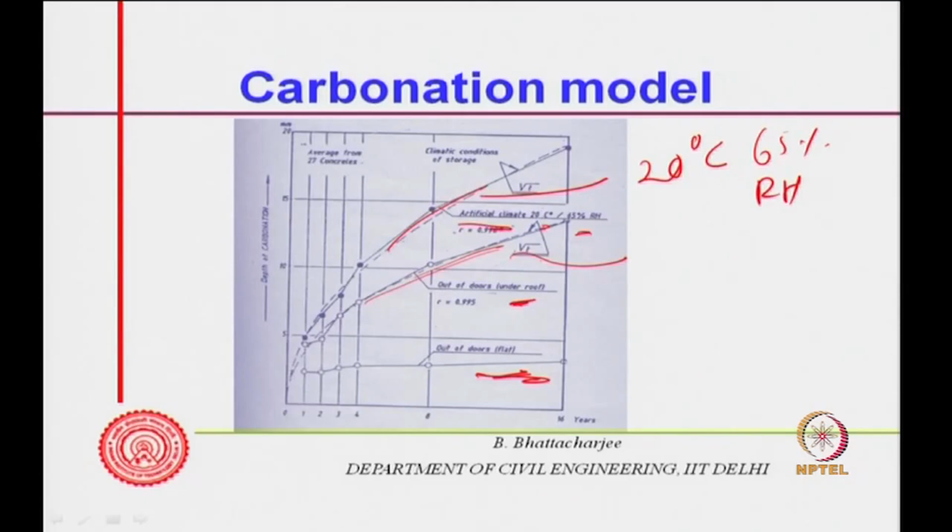So, what it shows is that the root T relationship is quite often followed. Although this relationship is very simple, depth varies with root time, and that becomes a kind of understanding that we develop from this situation.